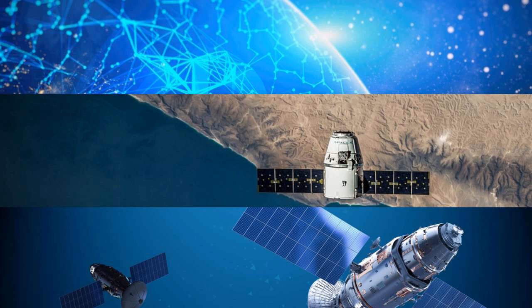In space, since convection and conduction are not available, the only way to regulate temperature is through radiation, which means the coatings are not secondary, but fundamental to the survival of the mission. This is exactly why Magic Black and Acktar White were paired for BepiColombo. Magic Black suppresses stray light inside the star trackers and spectrometers. It ensures that they can function even while pointing near Mercury's dazzling surface. And Acktar White protects the external surfaces by reflecting away the solar load and radiating away the excess heat, keeping sensitive electronics within safe operating conditions.